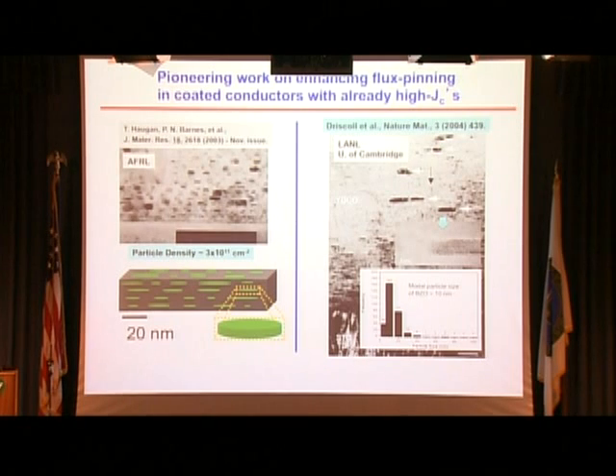They showed that we can, indeed, put nanostructures within single crystal superconducting films on single crystal strontium titanate substrates. In this case it is something called 211 within a superconductor, and in this case a whole random set of barium zirconate particles of this distribution within the superconductor, and they showed that you could improve the performance of a single crystal film.